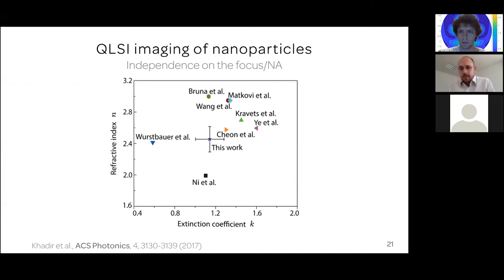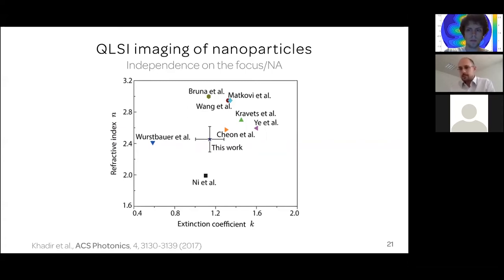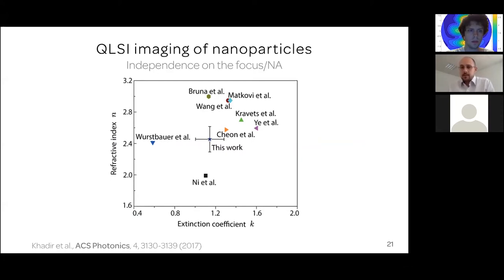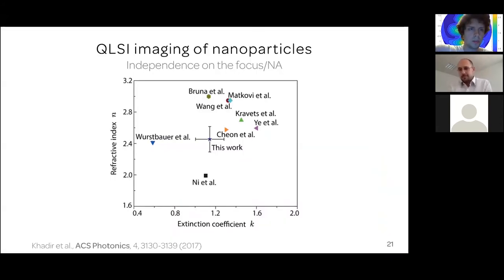The data in the literature are scattered — no two groups measure the same thing. This is not related to technique quality but more to the samples: graphene samples can be made in many different ways. In particular, you can have remaining polymer on top of graphene that you don't see with Raman spectroscopy. But you can see it clearly using quantitative phase microscopy. This is also a benefit of QLSI — you can test the quality of the graphene you are looking at.